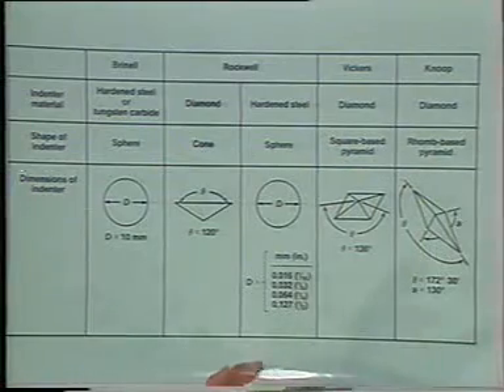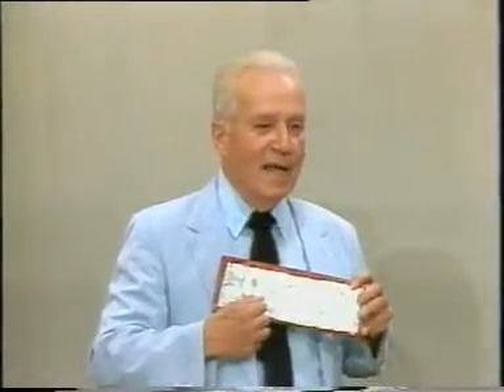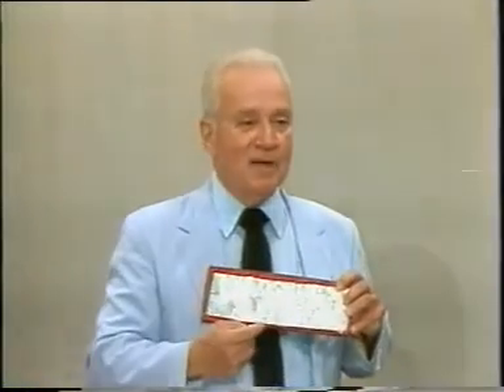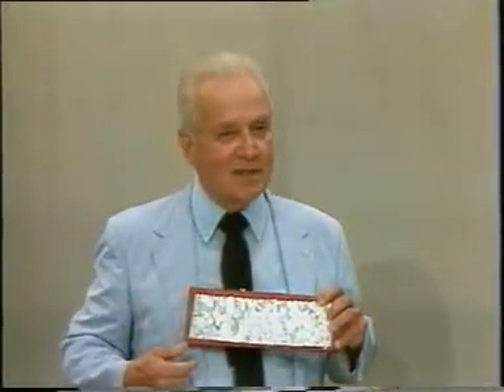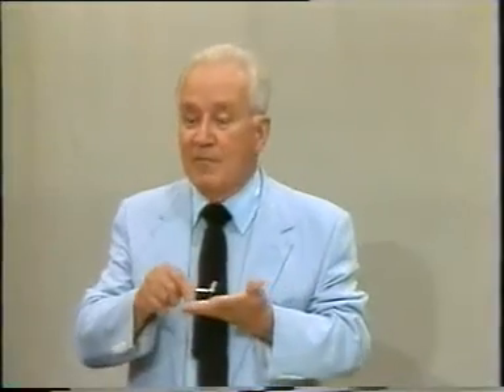Now, we do this on a macroscopic scale. Macroscopic meaning that I measure many, many crystals at one time in the Brinell hardness test. If the grain size is real big, if the crystal size is real big, as it would be in the board that I showed you this morning, and we put a Brinell impression on this, the crystal is bigger than the Brinell ball, so I'm going to be testing a single crystal, one single crystal. So many times since the microstructure controls what that stress-strain curve is going to look like, or what other properties are going to look like, I want to know not only what the hardness is macroscopically, I want to go inside the material and look at all of the different crystals, if you please, or the different phases that are inside, to find out what their hardness will be.